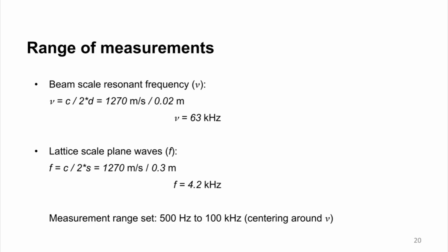And to include both in my measurements, I start measuring from 500 hertz to 100 kilohertz, and that way I have the first resonance of individual beams centered in this range. Because after perturbation there isn't a single beam length for a metamaterial like there is in an ordered point cloud, the beam lengths would be distributed around the length of the original point cloud, and so I would expect most beams to have their resonance distributed around 63 kilohertz, even though not exactly at 63 kilohertz.